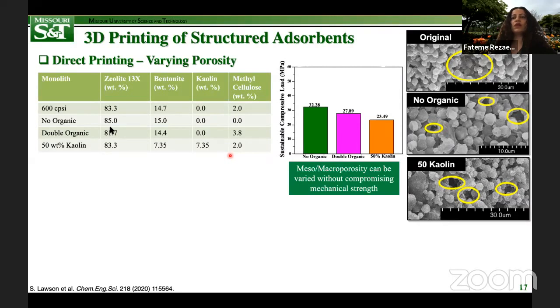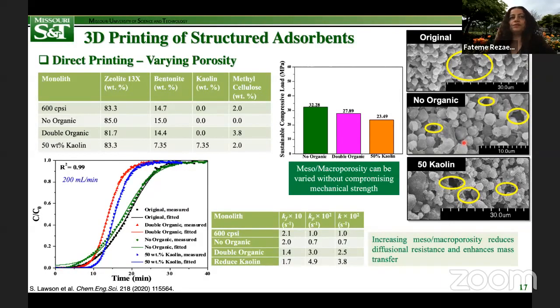Previously, in making these monoliths, we used a mesoporous binder, bentonite clay, and then in order to vary porosity, we decided to add a microporous binder such as kaolin to see how porosity could be tuned. And these SEM images visually depict the changes in the porosity of the monoliths and creation of meso and macro porosity upon variation of the composition. One thing that we found was that by doing this, the mesoporosity can be enhanced without weakening the mechanical stability, which was a great finding for our application.